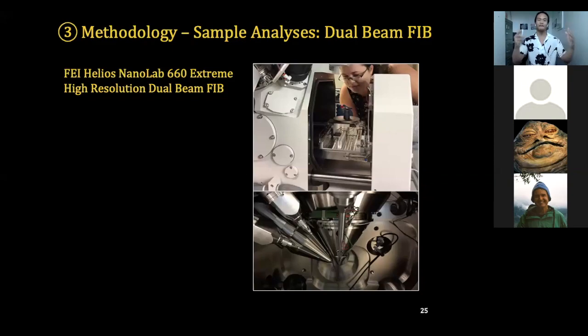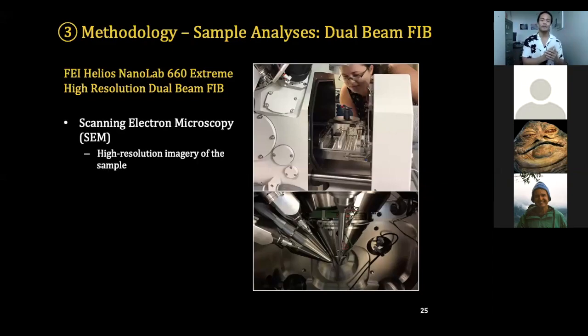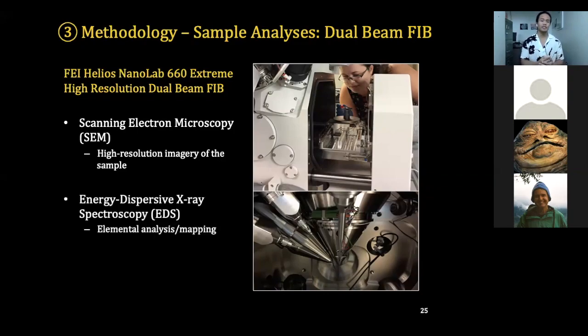What the FIB can do is, number one, scanning electron microscopy, or SEM, which gives us high resolution imagery of our sample. That gives us information on its textures, morphologies, and some of the features that are visible on the surface. It can also do energy dispersive X-ray spectroscopy, or EDS, which has elemental analysis and mapping capabilities. Finally, when we have a particle of interest, we want to be able to create a thin section of that particle, and we use the FIB for that. So the FIB is capable of doing scanning transmission electron microscopy, or STEM, sample preparation, which I'll explain later in the talk.